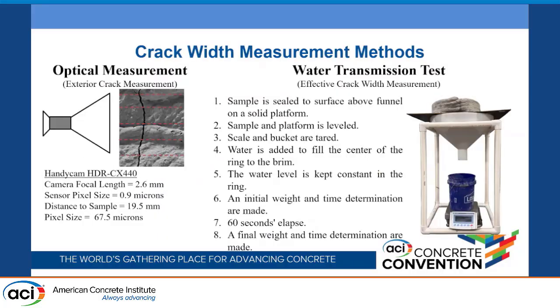After our samples were cast and cracked, we transferred them from the 50% relative humidity condition to a 23C, 98% humidity condition to allow for self-healing. While continuing with that self-healing, we carried out two different test methods.